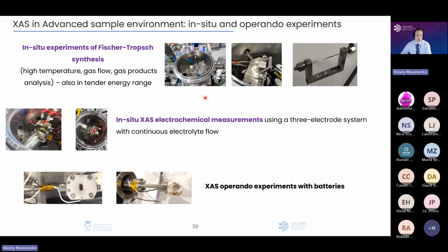It means that we can see what is going on with the material, not only before and after a reaction or heating, but what is going on when we actually make some kind of manipulation with the sample. Here, for example, we provide a complicated Fischer-Tropsch synthesis, and we have a catalyst in a capillary. We heat this capillary, the gas is flowing through it, and we investigate how the catalyst is changing during the reaction. Also, we could make different XAS electrochemical measurements in cells with flow of the electrolyte, without flow of the electrolyte, and also XAS operando experiments with batteries.